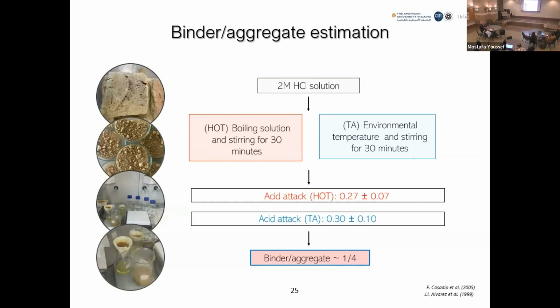After that, in order to characterize and go deeper with the analysis, I also did an acid attack. I used hydrochloric acid at 2 molar concentration, and I tested the mortar in 2 different ways. The first one used always 2 molar hydrochloric acid, but in a boiling solution for 30 minutes. In the other case, I also ran a 30-minute test, always with a stirring method, but with the solution at ambient temperature.